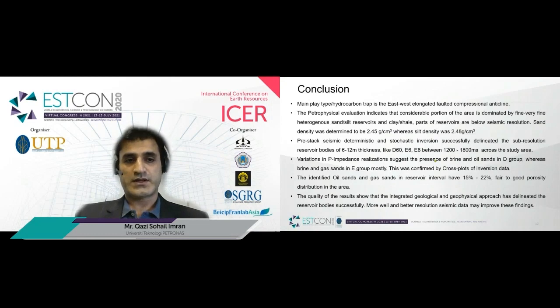Pre-stack seismic deterministic and stochastic inversion was used, which successfully delineated the sub-resolution reservoir bodies of 6 to 12 meter thickness, like D60, E6, E8, between 1200 to 1800 milliseconds across the study area. Variation in P impedance realization suggests there is a presence of brine and oil sands in the D group, whereas brine and gas sands in the E group mostly. This was confirmed, as I have shown, through the plotting of the inversion data as well.